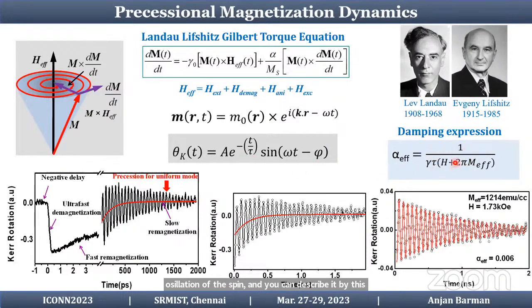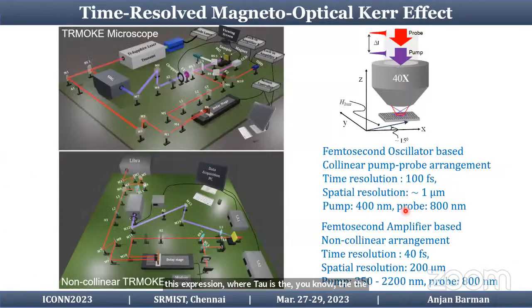And you can describe it by this harmonic function with a damping. And the damping, or the Gilbert damping, can be extracted by using this expression, where tau is the relaxation time of the precessional amplitude. So we measure it by using the time-resolved magneto-optical Kerr effect in our lab, which is an optical technique based on a femtosecond laser and an optical pump-probe technique.